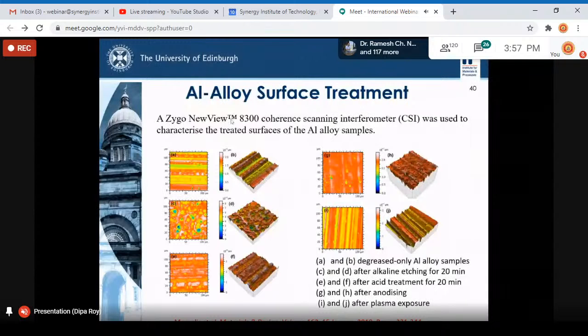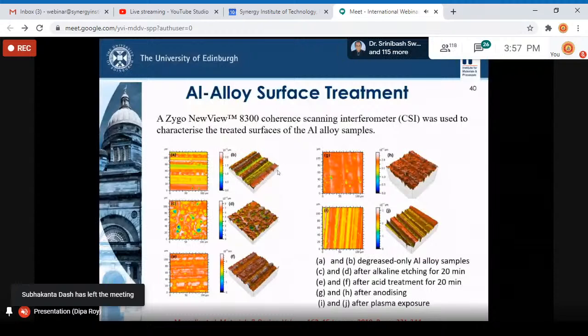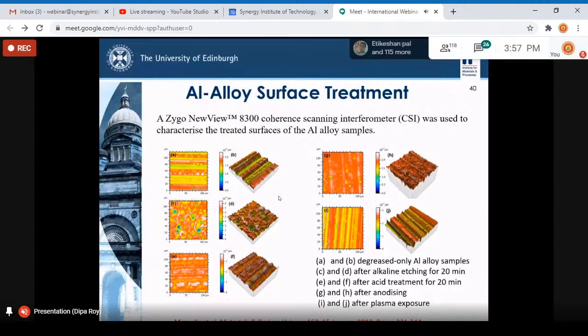So the first one, you see here, is the degreased aluminum alloy surface. We didn't do anything on this surface. The surface looked like this after degreasing and cleaning. And then we tried alkaline treatment, acid treatment, anodization, which is a more industrial technique, and also some atmospheric plasma. So with all these different techniques, we then investigated the surface morphology with a scanning interferometer, and we looked at how the surface of the aluminum alloys looked, and this was already published in 2019.